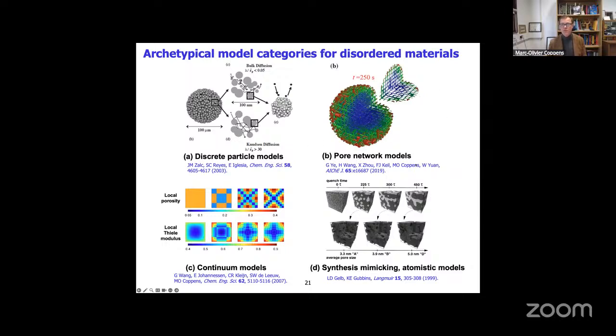Or we can use explicit pore network models. You see an example here on the right of some of our own work. Or we can go to continuum models, which doesn't mean you necessarily have the whole space as a continuum, but you can subdivide it into different areas so that you can include areas of various local properties, perhaps informed by magnetic resonance imaging, say, where the local porosity might be different and the local transport properties are different. And then this can help to optimize these materials as well, and optimize their overall geometry as part of maximizing, say, overall yields in a catalyst pellet.